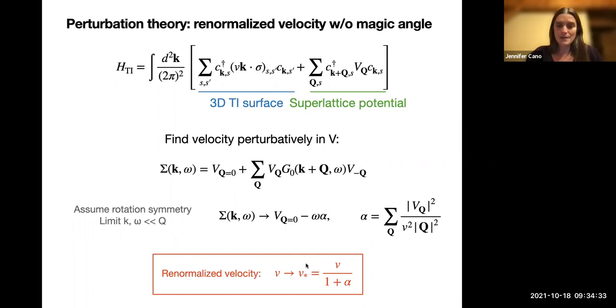However, one of the big differences is that in twisted bilayer graphene, you get these magic angles where the renormalized velocity is 0. And with this structure of V star, we never get magic angles. This function is never equal to 0. It just can keep getting smaller and smaller as we turn up the potential. So that's our first result, which is based on this perturbation theory.